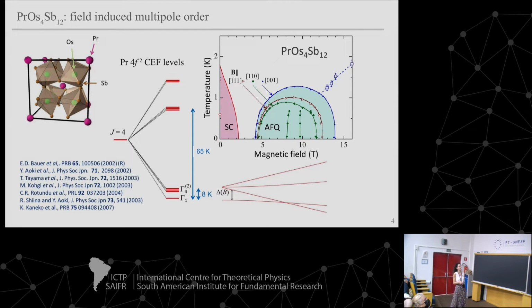So this is schematic. The levels don't actually cross. I'll show you something a bit more realistic in a moment. The excitation between these two levels. Now the ground state is the triplet level and the excitation. This is what these points were up here. As I said, I meant to take them off. I forgot. There is some anisotropy, but we see the same physics along all crystal directions, just with shifted phase boundaries. So there's not really a difference in physics, just a difference in the phase boundaries.